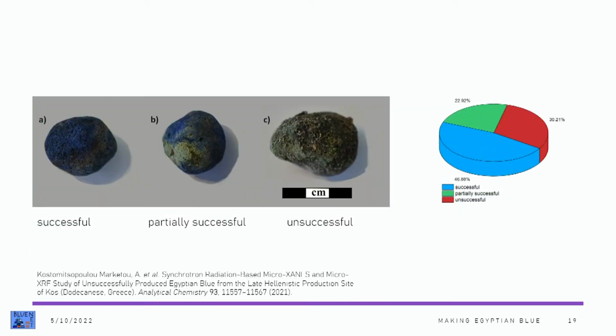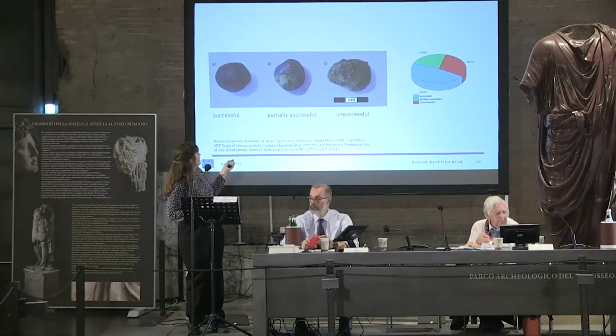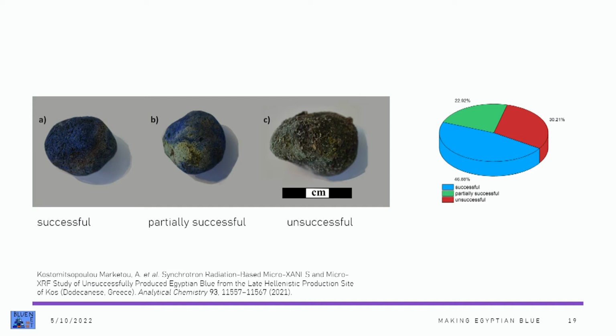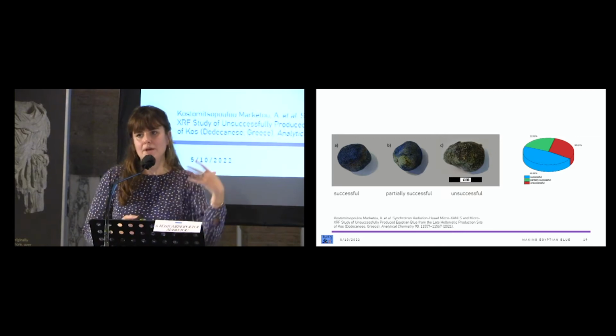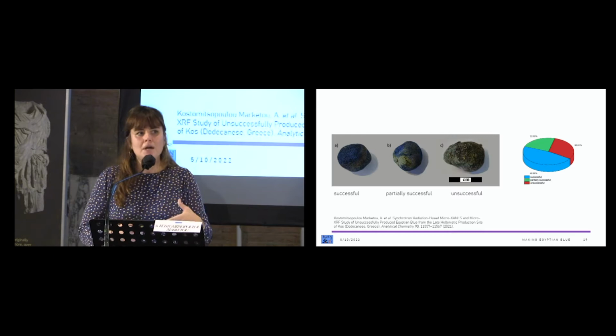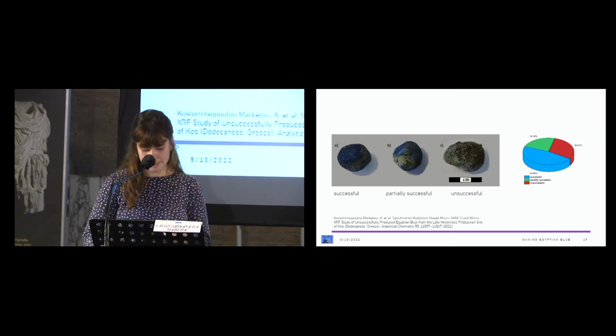As you can see, about half of the finds were successfully produced, like the first one here, with the characteristic deep blue color, while some were partially successful. They had visible blue, but also other, like green color was visible, and some were completely unsuccessfully produced. And the analysis suggests that the unsuccessful production was governed by improper, let's say, starting materials and the limited control of the craftspeople over the raw materials that they were using, therefore reinforcing the hypothesis of recycling of materials.